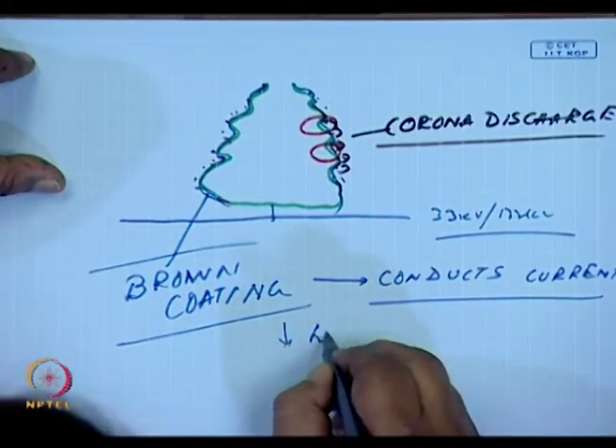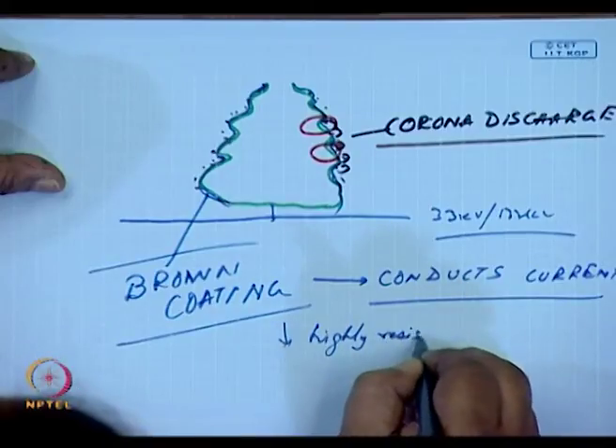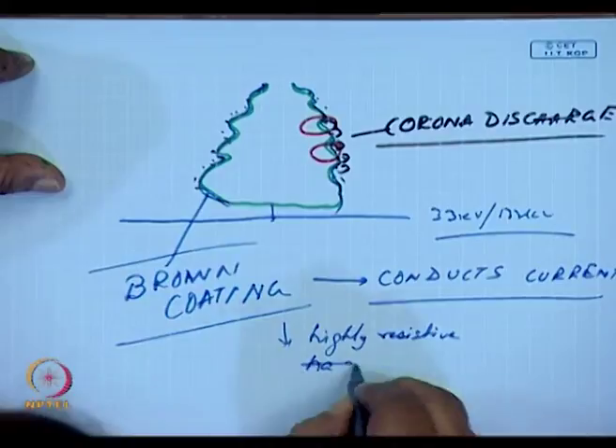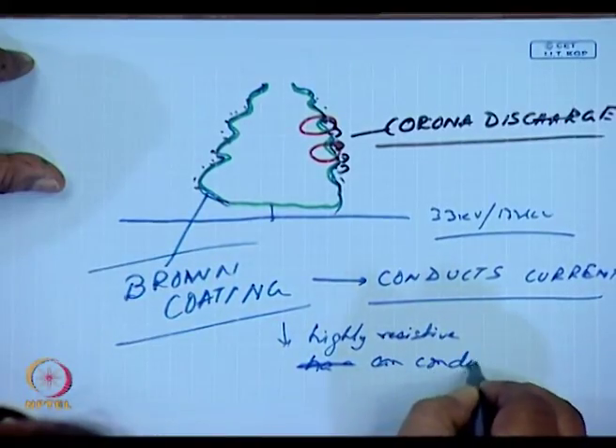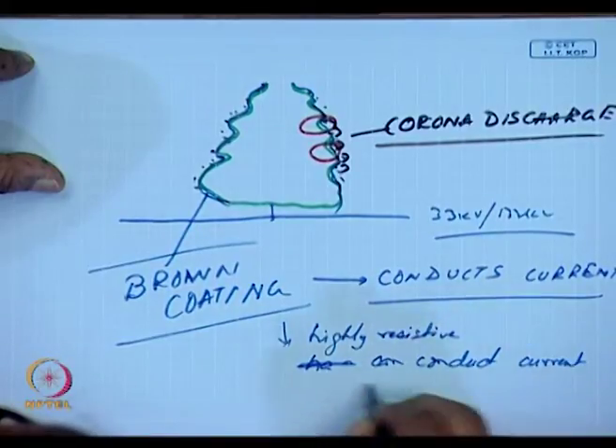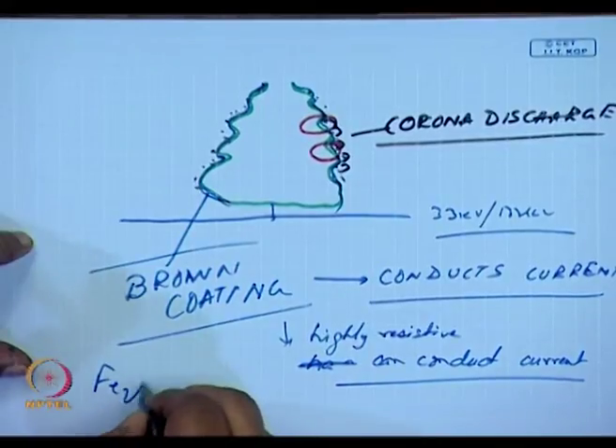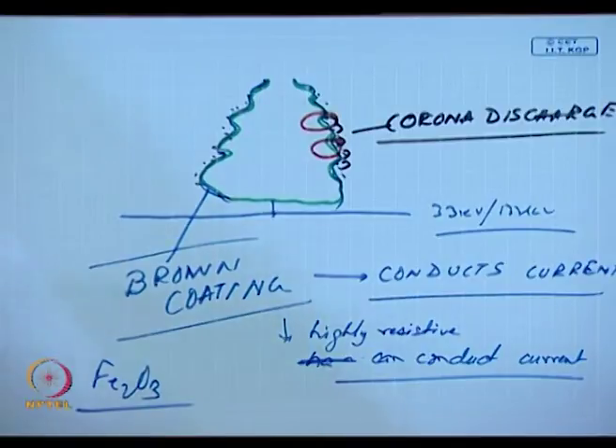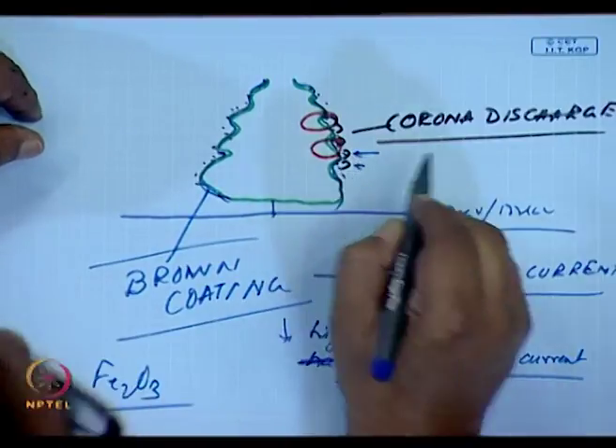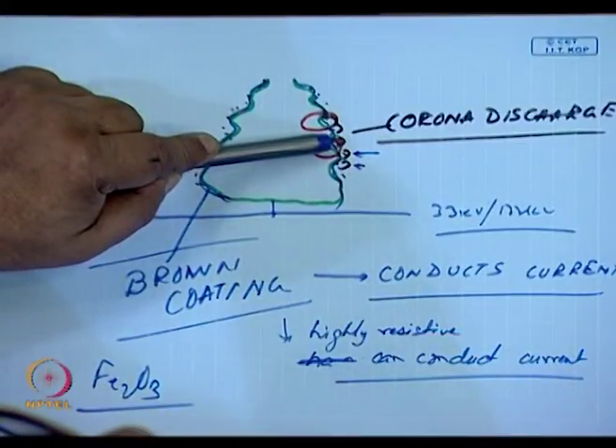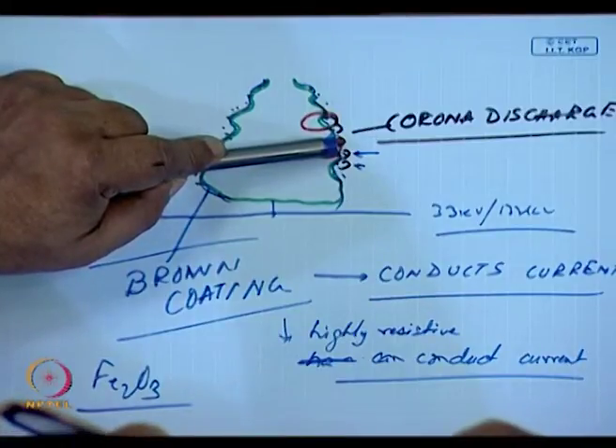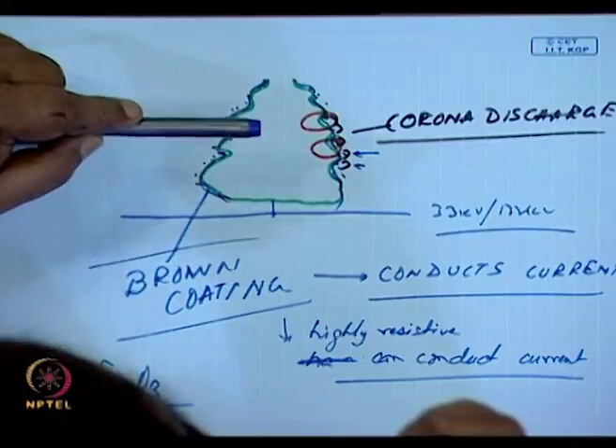It is highly resistive, but can conduct current, and it is based on Fe2O3. It is an iron oxide based coating, which by normal means is highly resistive, but if such corona discharges occur, as I have said over here, under the action of the corona discharge, it provides an alternate pathway so that arcing or sparking, if you prefer the word, does not occur at these points and avoid catastrophic failure of these high tension insulators.